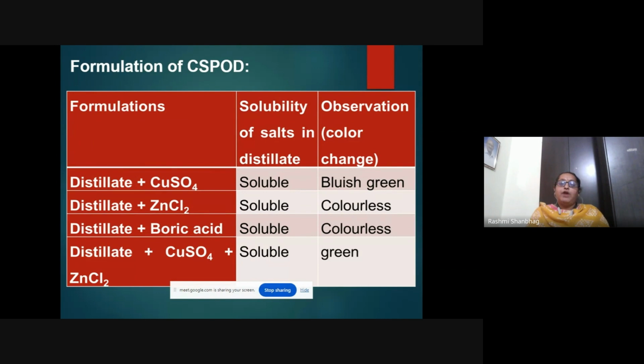So we have to mix it with some inorganic salt. We actually tried different materials like copper sulfate, which acts as a fungicide, zinc chloride, and boric acid, which acts as an insecticide. In case of wood, fungus and insects are the main agents of degradation. We also used a copper sulfate and zinc chloride combination.